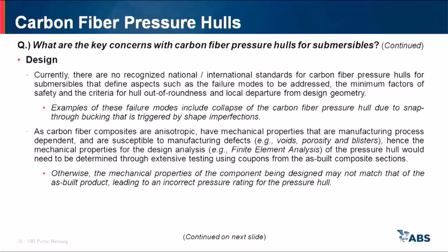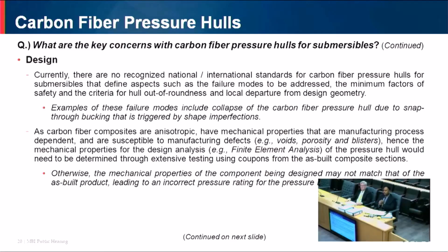We had a look at the testing requirements. Many of the testing requirements are geared towards internally pressurized pressure vessels. We didn't see any specific testing requirements for externally pressurized pressure vessels. Okay, so these are some of the shortcomings of Section 10. And this section is not applicable to manned pressure hulls, okay? Nevertheless, it has a lot of useful information. It has acceptance criteria for voids, delamination, cracking, etc. The important thing is this code states that for a new construction pressure hull, no delamination and no cracking in the matrix is permissible, okay? So if you have a new hull with delamination or cracks, it is not acceptable as per this code.